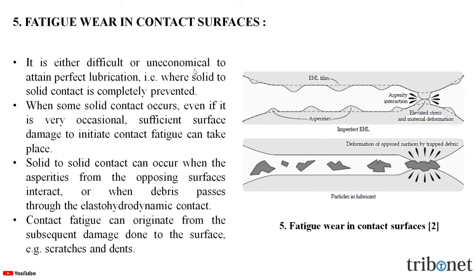Now let us understand fatigue wear in contact surfaces. It is either difficult or uneconomical to attain perfect lubrication where solid-to-solid contact is completely prevented. When some solid contact occurs, even if very occasional, sufficient surface damage to initiate contact fatigue can take place. Solid-to-solid contact can occur when asperities from opposing surfaces interact or when debris passes through the elastohydrodynamic contact. Contact fatigue can originate from the subsequent damage to the surface.